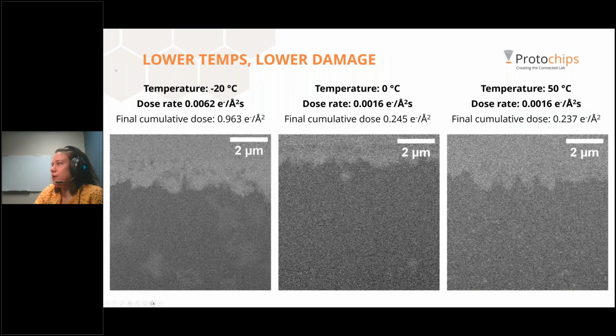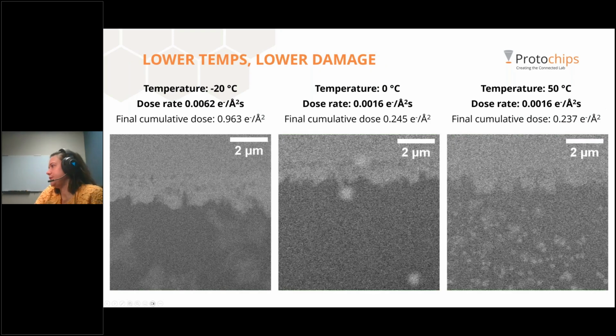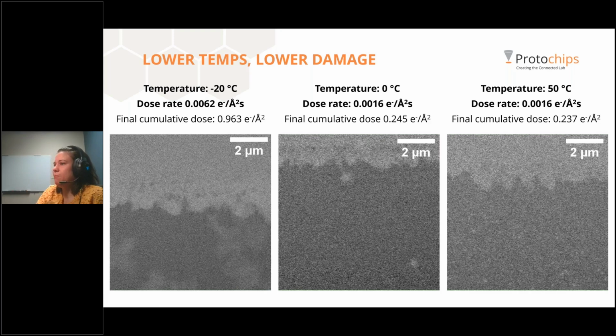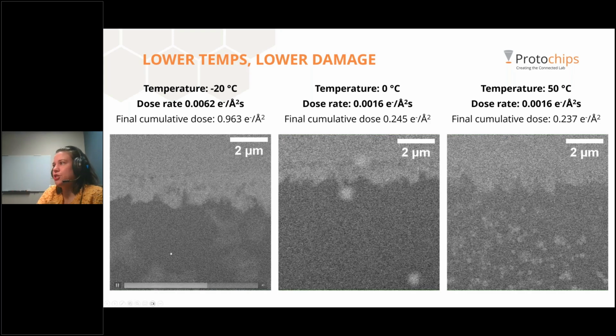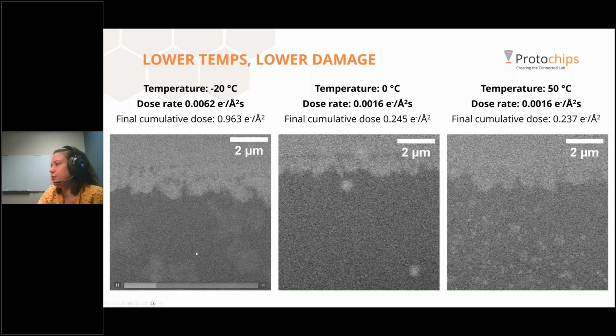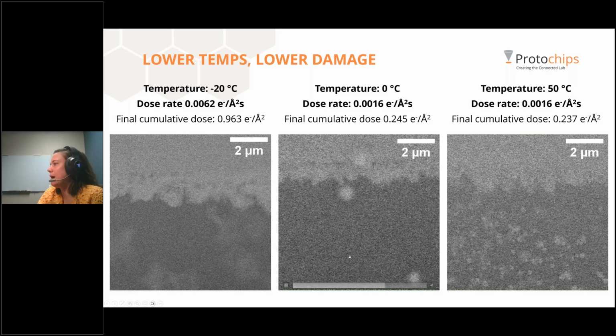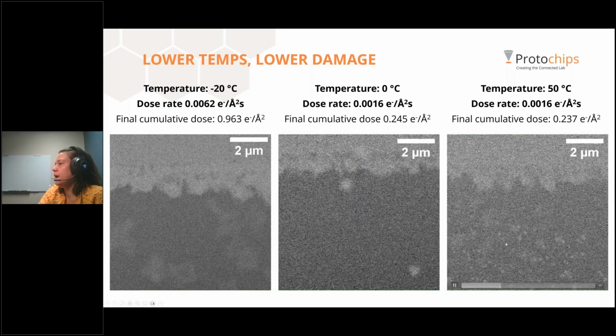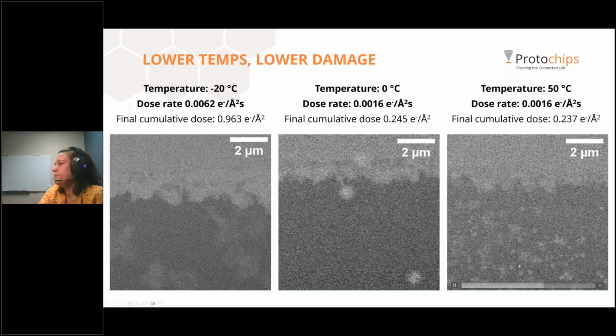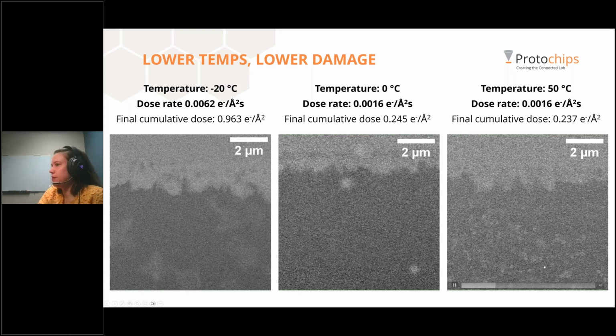And so -20 is on the left, 50 is on the right, and you can see at the very bottom, the -20 doesn't seem to change very much. The 0 changes a little bit, and the 50, you absolutely see growth induced by the electron beam rather than the experiment itself.